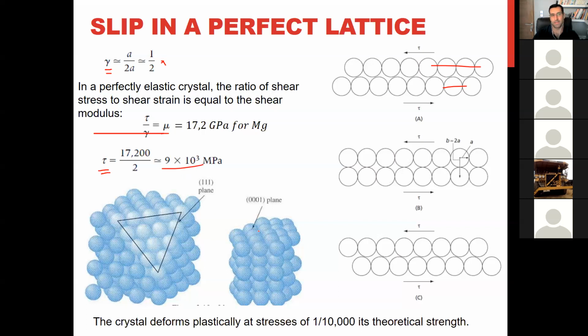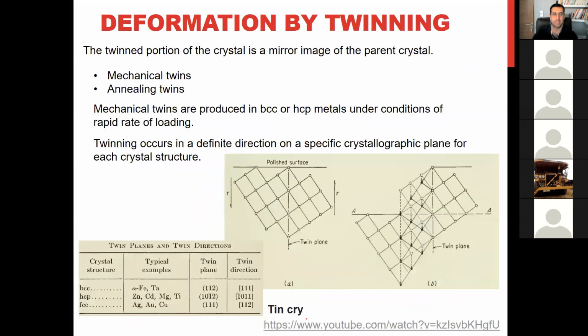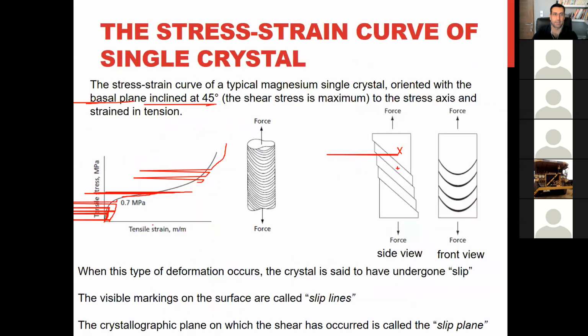It means applying shear stress in this way. Theoretically, for this movement of, for example, two planes of this crystal, you need theoretically 10,000 megapascal. That is much more than what we see here. It's about 1 megapascal.